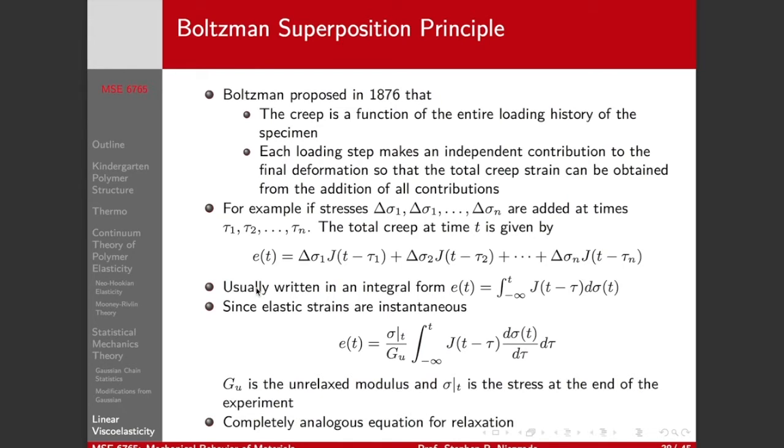An important concept to help analyze the viscoelastic response or the linear viscoelastic response is this idea of the Boltzmann superposition principle. And Boltzmann proposed way back in 1876 that the creep is a function of the entire loading history of your sample. Each loading step makes an independent contribution, but you need to consider all those contributions independently. And there's some equations here and they might not make a lot of sense until we look at it kind of conceptually.